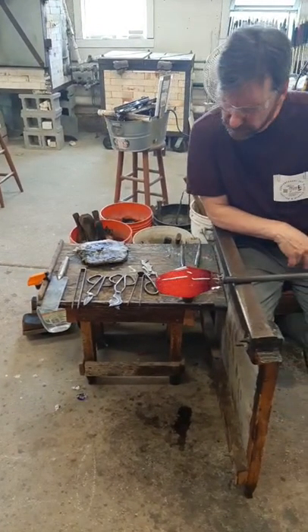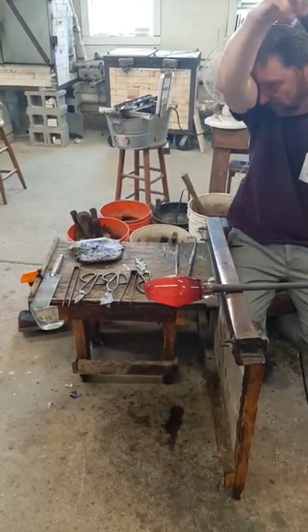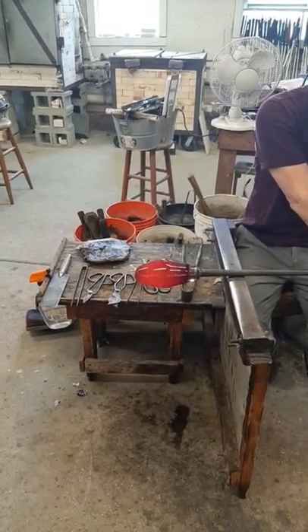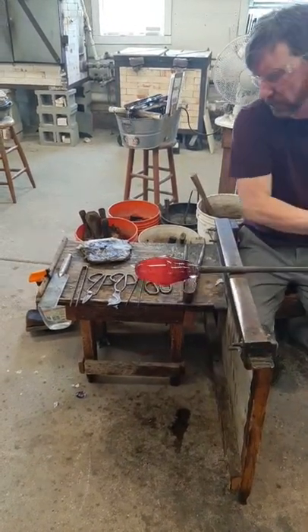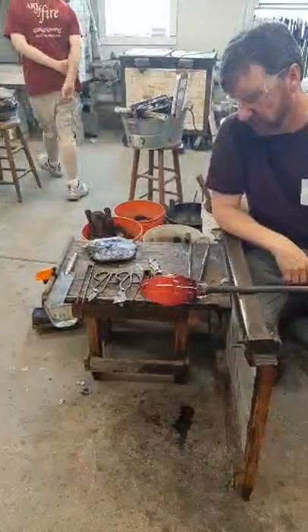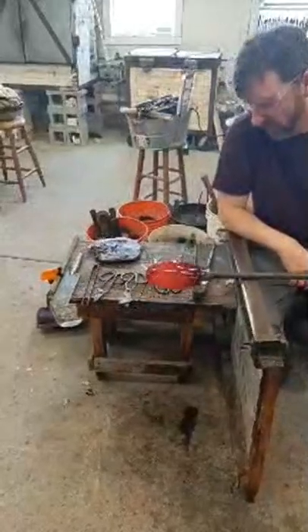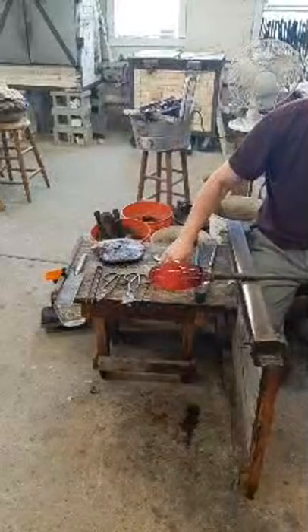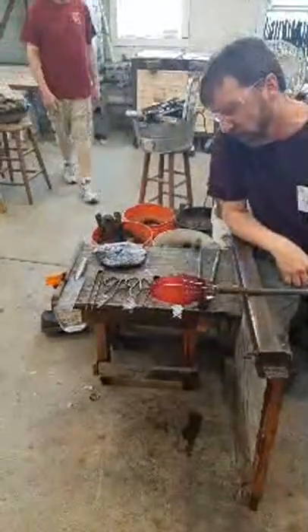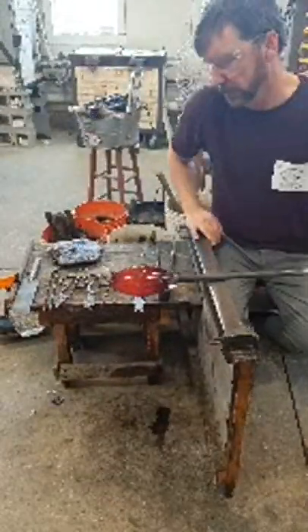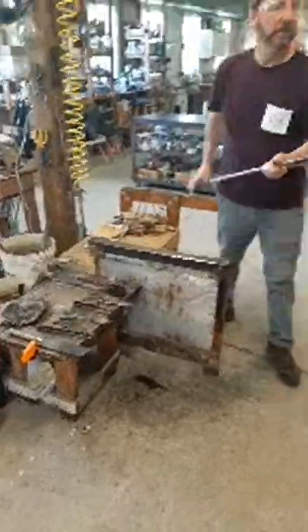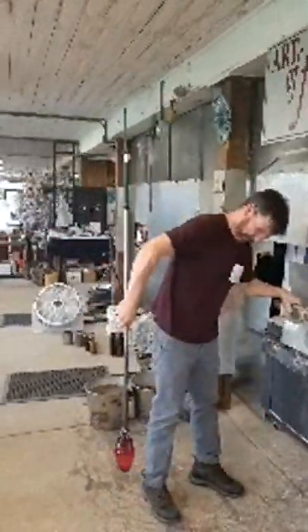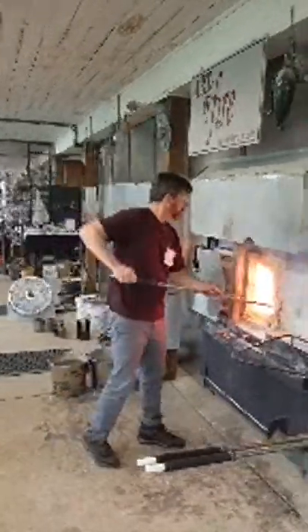So we've got the fire polishing. The other term was the air marvering. Air marvering is just like it sounds, letting the glass shape in mid-air. And then what we're doing is we're not just idly standing by whistling a happy tune. Sometimes we're seated. No. What we do with the air marvering is we use the rotation of the iron, the loss of heat, and gravity if need be, to keep the glass centered and let it cool off uniformly. So what Todd's doing right now could be accomplished much faster on the marver, the cooling, but again, as he said, it would cause marks in the glass, chill spots, wherever it touched the metal. So that's what he's avoided, and now with this even larger gather of glass, he'll gather once more.